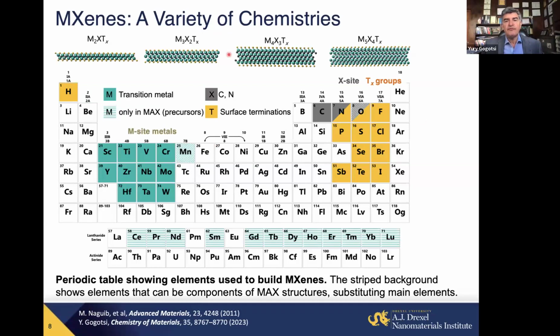So if you just take 4 basic structures with 2 to 5 layers of transition metals, a dozen transition metals, carbon, nitrogen, carbide, or nitrides, you will end up with close to 100 possible combinations. Take another dozen surface terminations, you end up with about 1,000 possible combinations. Not all of them may be thermodynamically stable, but there are actually many others which I'm not showing here. So we can have at least 100 to 1,000 new stoichiometric materials that can be created. But we can also mix and match different elements, making an infinity of new materials.